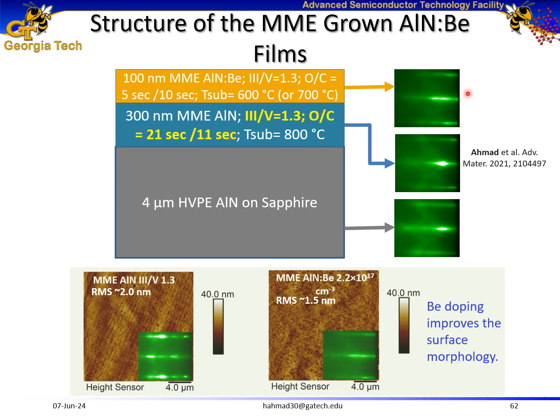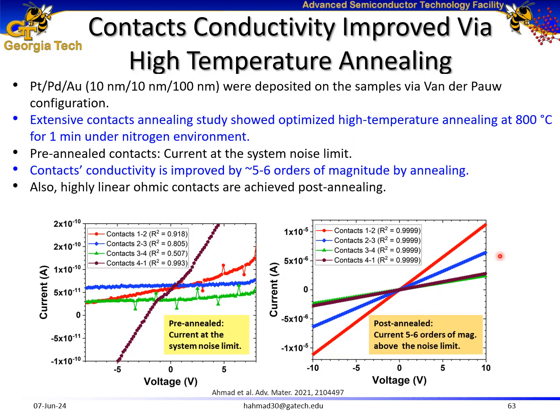We achieved streaky reflection high energy electron diffraction patterns indicating smooth surface morphology. From AFM comparison of a beryllium-doped aluminum nitride versus an undoped control sample, we see that beryllium doping improves the surface morphology. Later, I deposited platinum, palladium, gold contacts on these films for Hall measurements. And from extensive optimization of the contacts, here I've shown a comparison of the post-annealed beryllium-doped aluminum nitride versus pre-annealed contacts. And the annealing improves contact conductivity by approximately 6 orders of magnitude.